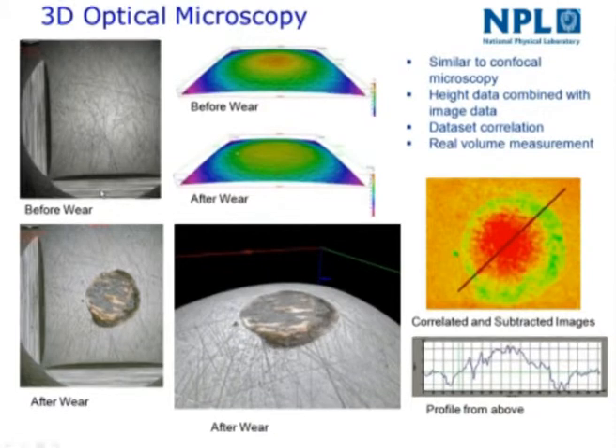And this shows the slide I mentioned earlier. This is 3D optical microscopy, and here you can see the results of a test. This is looking at the steel ball that we rubbed against a DLC coating. This is before the test, and this is after the test, and you can see the wear scar here. You can see there's a transfer layer, and you can see that there's some material that's built up on the surface. What you can do with these microscopes is you can look at height maps.